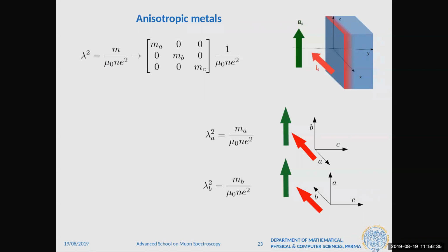No. You will see that the most used way of measuring these parameters is not in the way I explained here, but through the flux lattice. And there the trick is that it doesn't really matter where the muon ends up, because the flux lattice is incommensurate with the lattice. Then the subtle part is that if you have very flimsy superconductors, then the muon might locally interfere, and the muon is measuring locally.